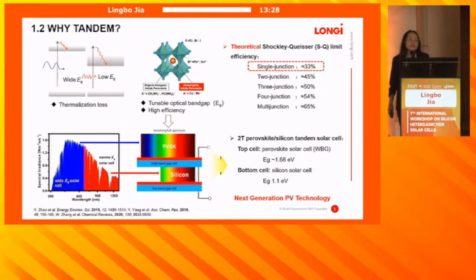As we can see, narrow bandgap silicon solar cells face a keen challenge of thermalization losses, which can significantly impact the device performance. And the perovskite materials have an ABX3 structure, where the A site usually is organic cations, the B site is metal ions, and the X site is halide ions. The perovskite materials have many outstanding properties, including the tunable optical bandgap and high efficiency. The theoretical SQ limit efficiency of a single junction is around 33%. So it is urgent to develop new techniques to further improve the device efficiency and break through the SQ limit.